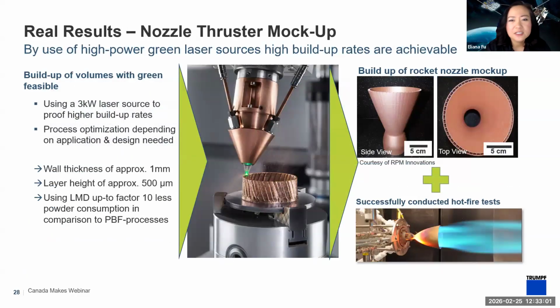And here's an example. I did have this nice image on the front page of my webinar, just showing you some build-ups here with the green laser. This was using up to a 3 kilowatt green laser to make these kinds of nice structures. Some of our customers have actually used this on real components, not just rocket engines, but also small thrusters, and successfully conducted hot fire tests, which are kind of interesting. Typically the factor is about 10 times less powder consumption compared to a powder bed process.